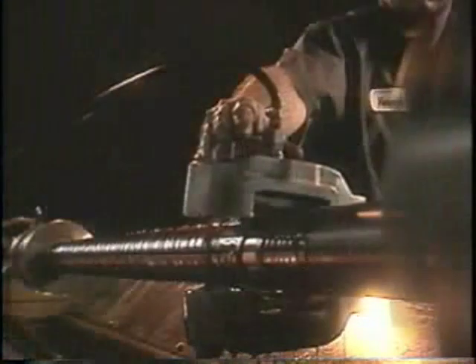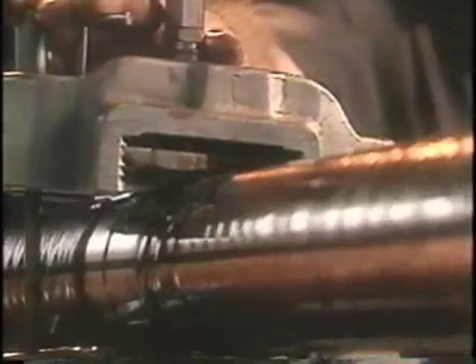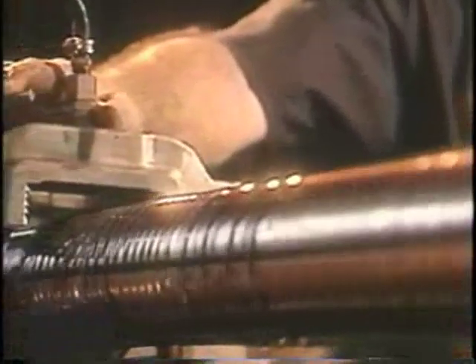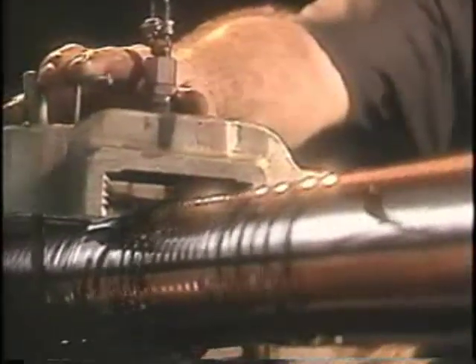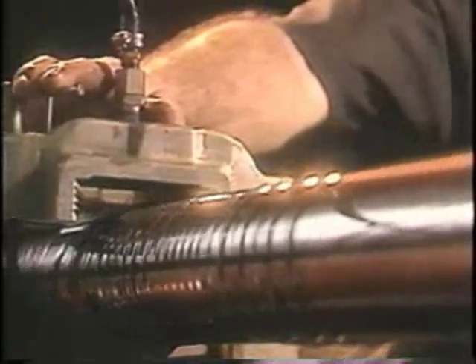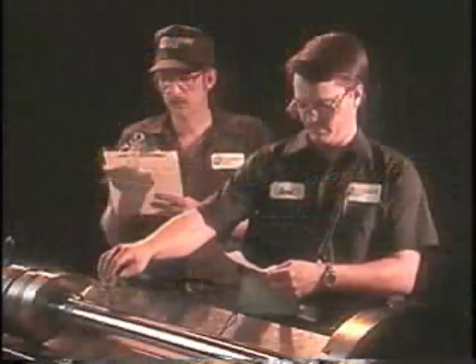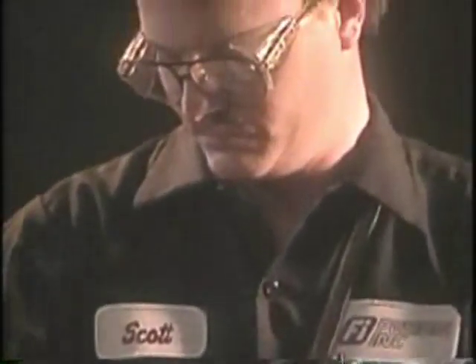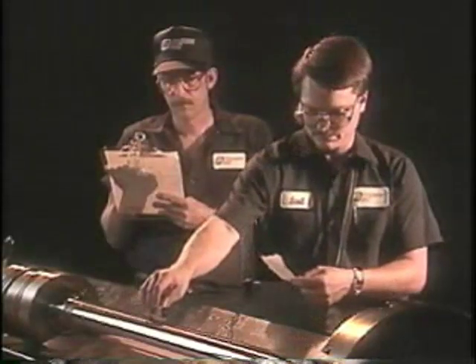After grinding, every part is given a dye penetrant check to be sure there are no blisters, cracks, or pits. The part will be honed and super finished to the specified RMS finish. Generally, a 12 to 16 RMS is called for on rotating equipment. On this compressor rod, though, the surface will be finished to 8 to 10 RMS. And if it's required, a 2 RMS finish is attainable. The surface finish, dimensions, and runouts are recorded on a final inspection sheet. This information is kept in the job file for future reference.